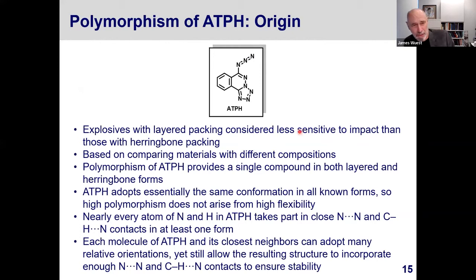This is interesting because in the field of explosives, there's a general consensus that explosives that have a layered packing are less sensitive to impact than structures that have a herringbone pattern. And this appears to arise because if you subject a compound that's layered to an impact, the layers can slide over one another. And in the herringbone case, molecules are forced into one another.